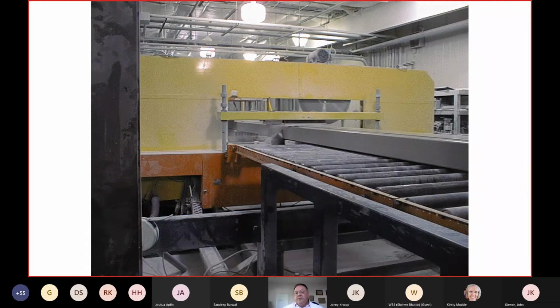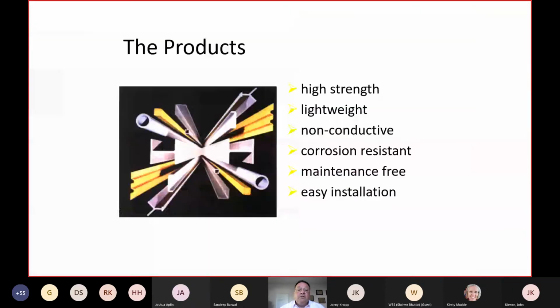And this material will come through the machine at anywhere from 0.5 meter per minute to 2.5 meters per minute, depending on the wall thickness of the part you're trying to make. They can pull it through and cut it off very accurately right here in the factory to the lengths that you need, and therefore there's no waste. Once we do that, we make these parts.